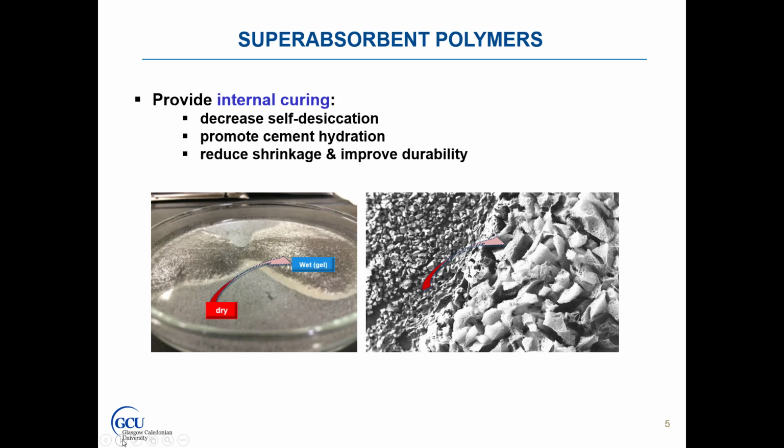Its high capacity to absorb water from the fresh mix and release it over time can control autogenous shrinkage in early ages. Additionally, when SAP collapses, it leaves behind pores that can significantly change the microstructure of hardened concrete and provide more room for later product deposition.